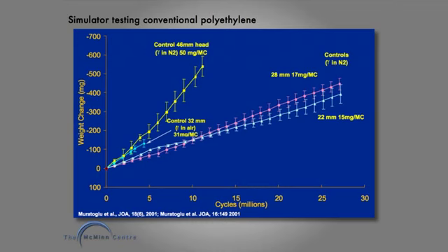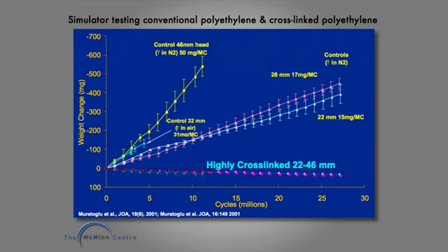When the same simulator studies are done on highly cross-linked polyethylene, there is no wear difference in the range of 22 to 46 millimeter heads. So if we would today want to design a hip resurfacing with polyethylene in it, for sure, because of the inevitable use of a large head size, we would want to use highly cross-linked polyethylene.